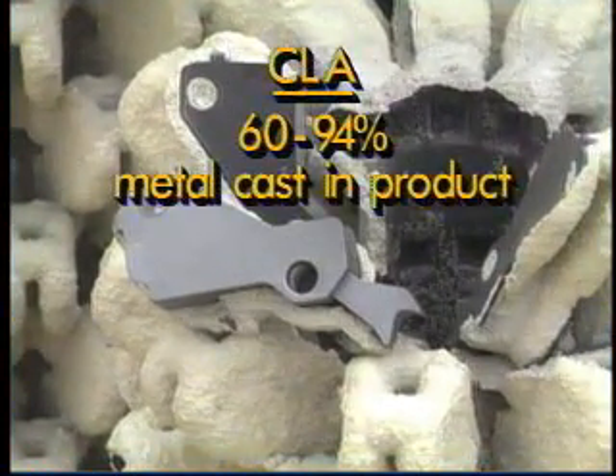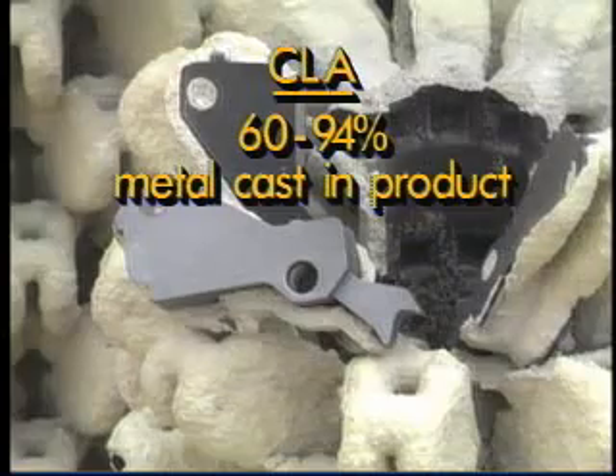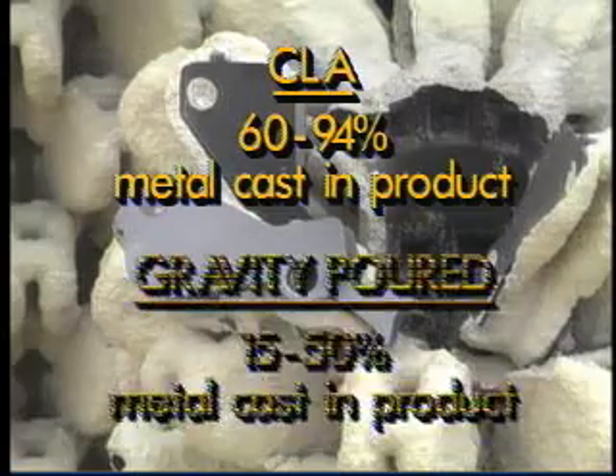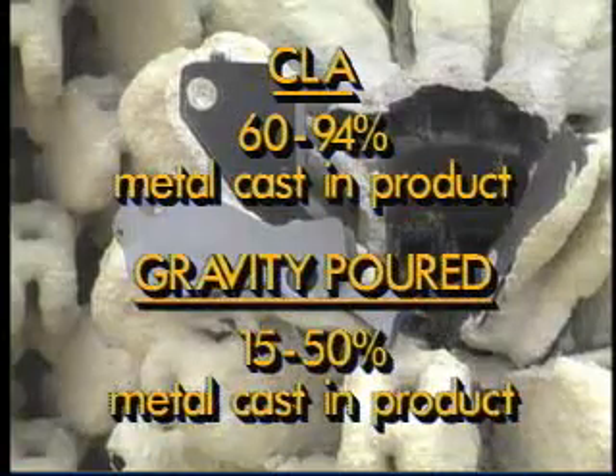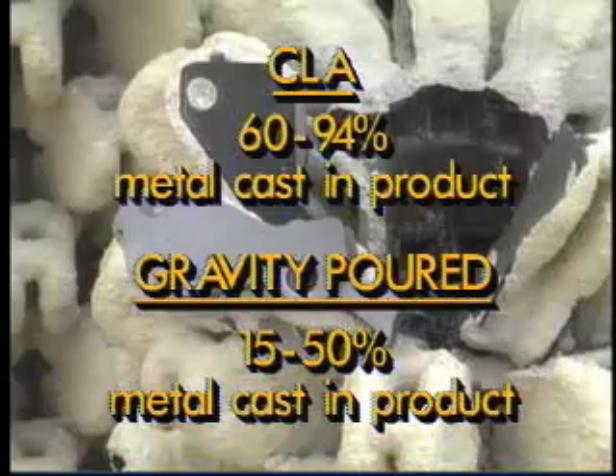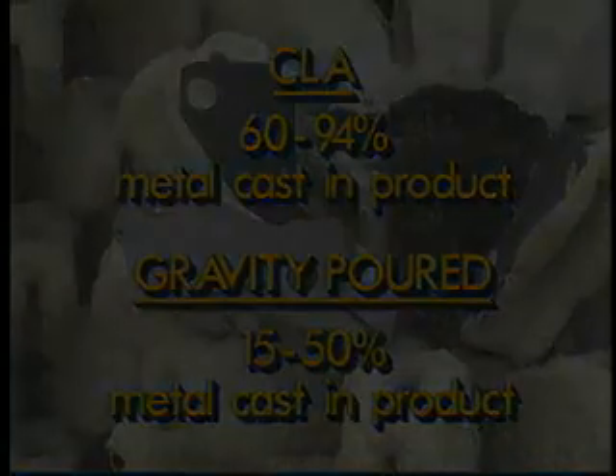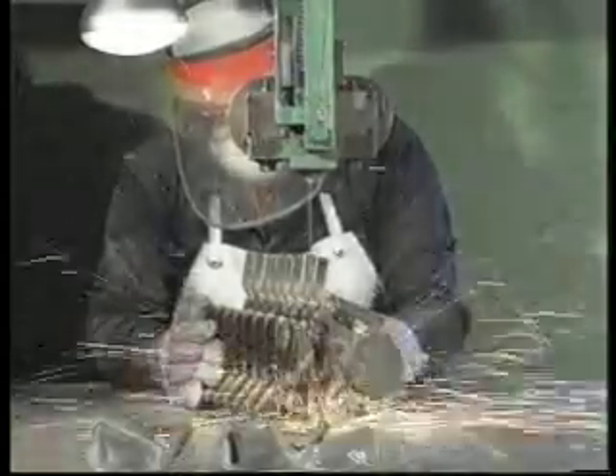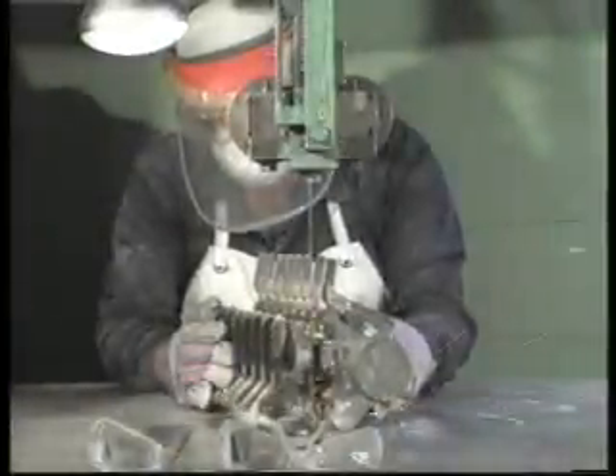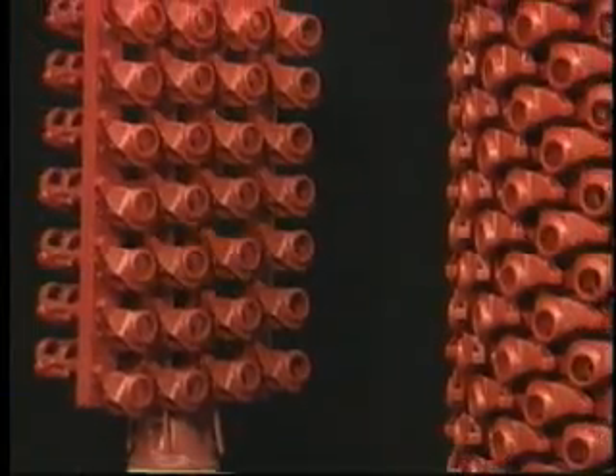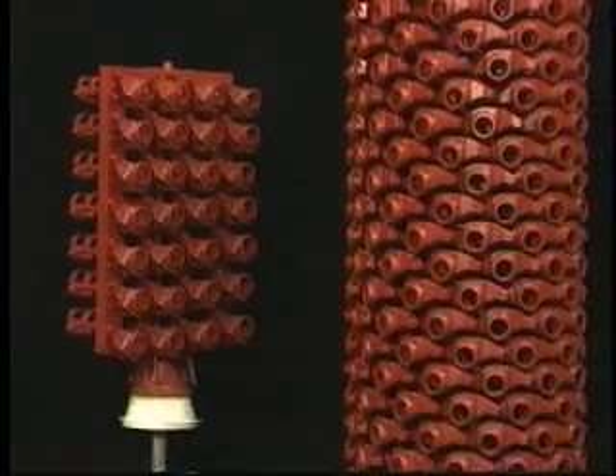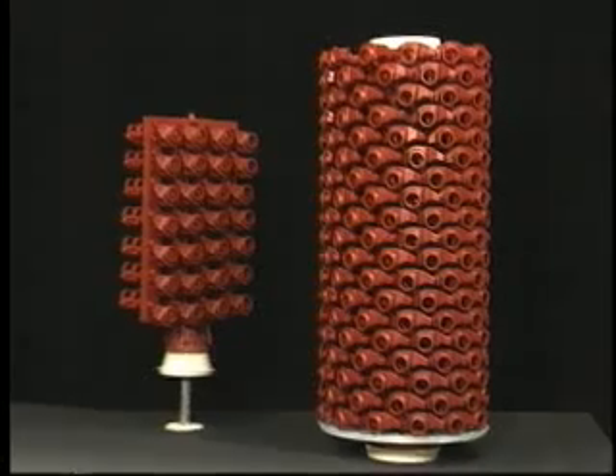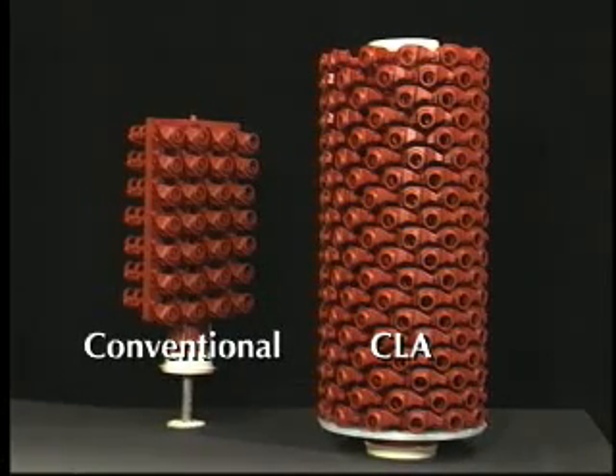As a result, 60 to 94% of the metal cast is used to produce the product, as opposed to 15 to 50% in gravity poured parts, where much of the cast weight is in the sprue and gating. Unlike gravity poured parts, which must be cut away from the central sprue, there is no need to leave room for the cutoff blade in the design of a CLA casting cluster. As a result, many more patterns can be assembled on a CLA sprue. The increase in pattern population per sprue may be 2 or 3 times greater than conventional assemblies, depending on part size and configuration.